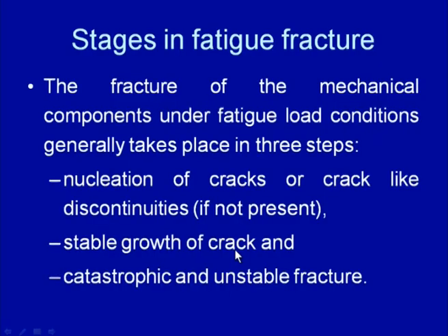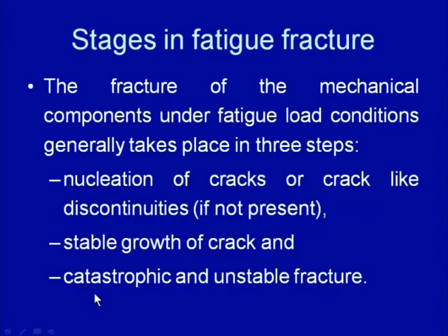The second stage is the stable crack growth zone, where the crack grows in a very stable manner, slowly, and this stage offers the most useful part of the fatigue life of the component. And in the third stage, when the cross sectional area of the component is reduced to a greater extent, catastrophic failure takes place.